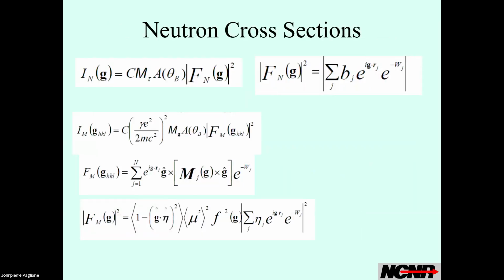Neutron scattering, you typically have 2 different contributions. So the nuclear scattering, basically the structure factor here has a scattering amplitude, because I remember that I told you that the nucleus looks like a point particle. And so there's just a number, and you don't have to worry about the spatial distribution. And you just look those up. So if you're doing, say, a profile refinement for crystal structure, that makes life easy. And then you just do the usual sum over the unit cell.